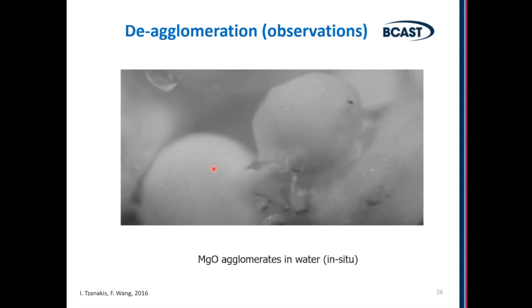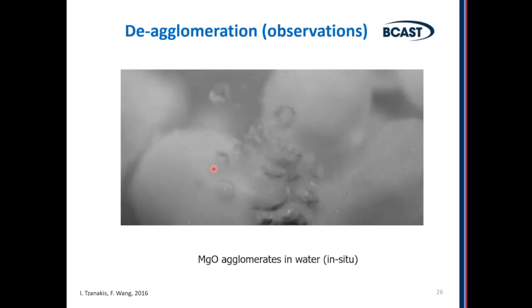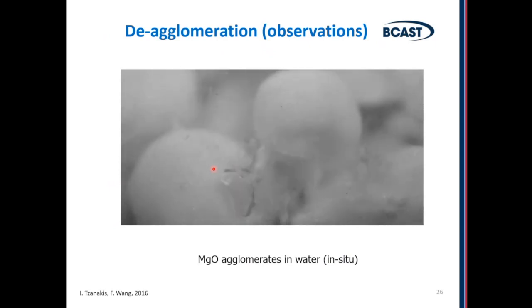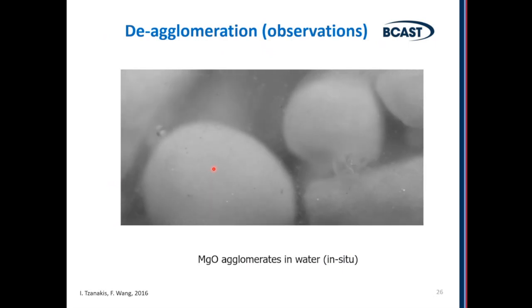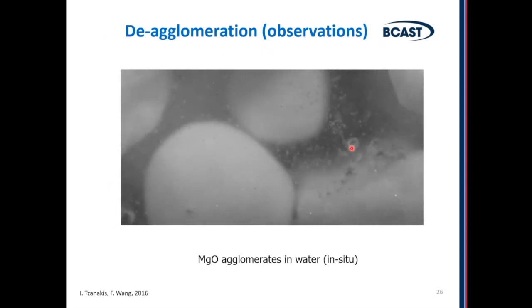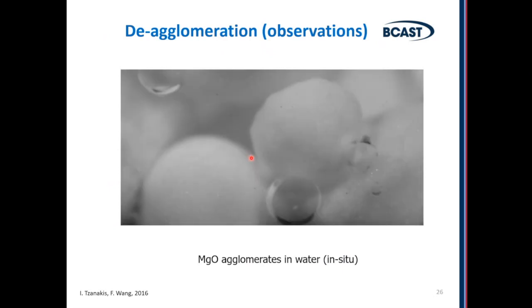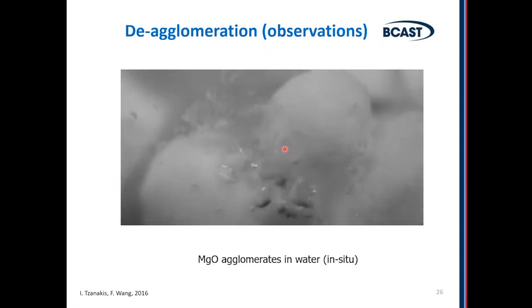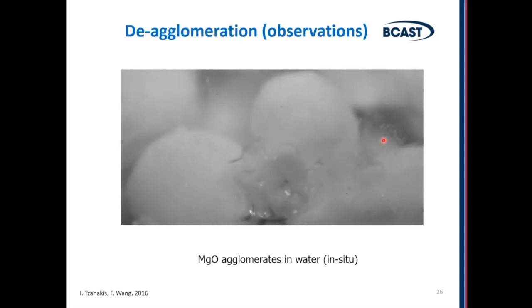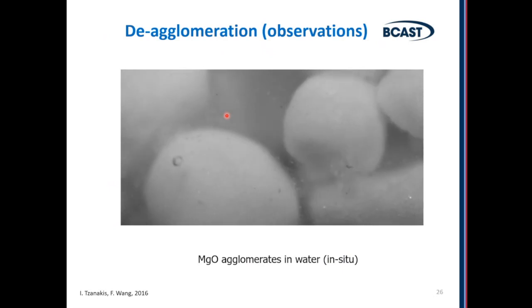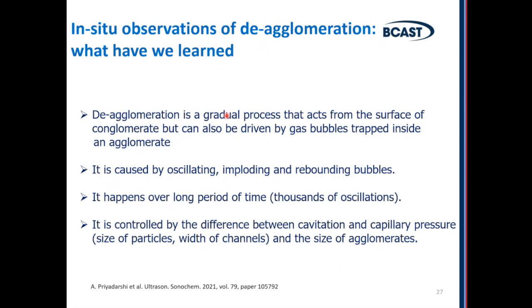Another thing is deagglomeration. If you have agglomerates of particles, for example when you add particles into liquid aluminium to make a composite material, they tend to agglomerate. And what cavitation does, these cavitation bubbles scrub the surface of these agglomerates and deagglomerate them. So instead of having big chunks of agglomerates, you have individual small particles released into the liquid. What is important is that it's a gradual process, it takes a long period of time. So if you want to make nanocomposites by adding nanoparticles into aluminium melt, you need to allow some time, 10, 15, 20 minutes for the process to happen. If you try to do it in 10, 15 seconds, you will not be able to achieve the result because of the mechanisms of deagglomeration.